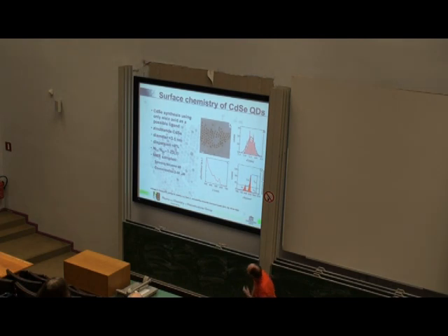The first thing I would like to show you is just the TEM image of selenide quantum dots. Before that, a number of basic material properties. So here you get, again, a TEM image. It's a bit zoomed out. We don't see the atoms here. The dark spots that you see are just individual nanocrystals. You can see they have a size of something like 3.5 nanometer. Here is a size histogram. We have a size dispersion of about 8%, something that is quite important for later on.